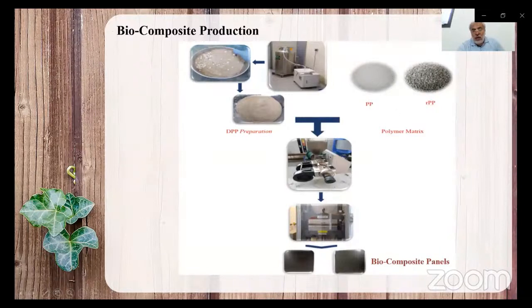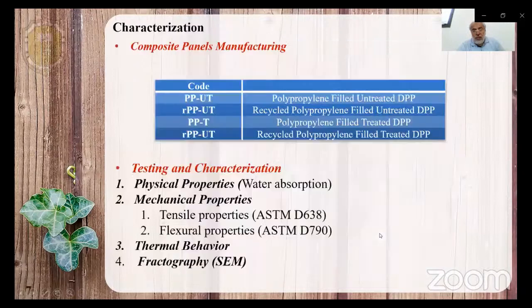So we use a twin screw extruder to mix the two ingredients in a melt state, and then we compress it in a compression machine to make panels to be tested.